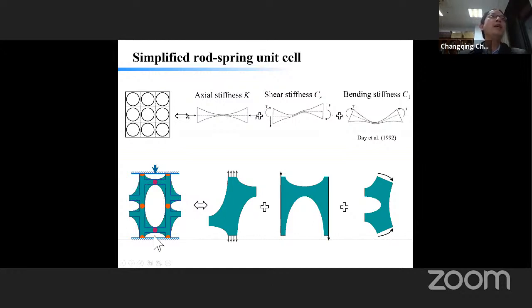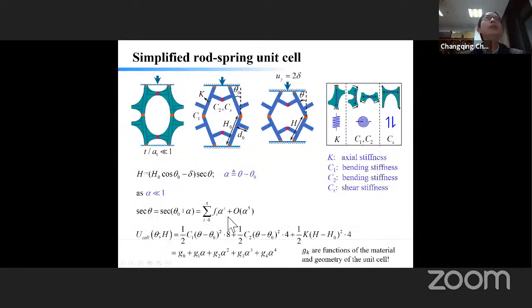we simplify our unit cell with strut. So again, we have axial stiffness. So we load it in this way. We have axial stiffness, we shear it, we have shear stiffness, and we bend it, and we have bending stiffness. So now we have a number of hinges. We use springs for this unit cell, and now we can have a simplified rod-spring unit cell. So we have tensile stiffness K, and we have shear C1, C2, and we also have CS. C1, C2, sorry, is actually bending.